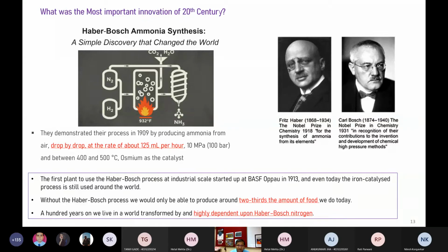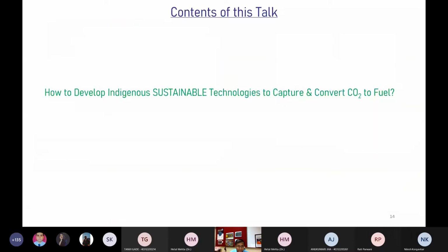where you need to develop different kinds of materials. And I will show you how I tune the properties of the material so that I can tune the catalytic activity of that material. So tuning of the properties can be achieved by tuning the particle size of the nanoparticles, the shape of the nanoparticles, morphology of the nanoparticles. So nanoscience and nanochemistry gives you these handles to tune the properties of the material by simply changing their size, shape, morphology, say some defects or interfaces, and using that one day we will be able to produce a process which is commercially viable.